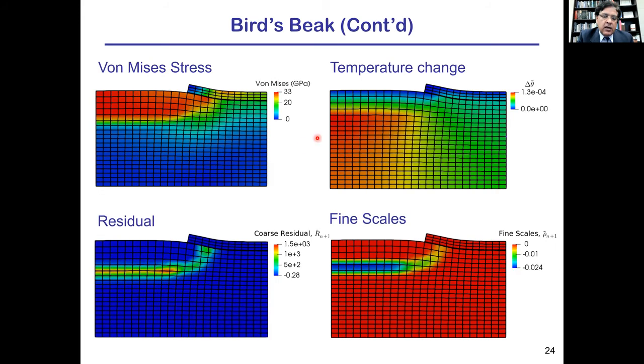Here is a snapshot at one of the points along the deformation, frozen in time. So we have the von Mises stress distribution. This is the advancing front. This is the temperature change, and we see that temperature is higher in the region where the reaction is taking place. We also see that the residual is higher in the elements that are being traversed by the advancing front.